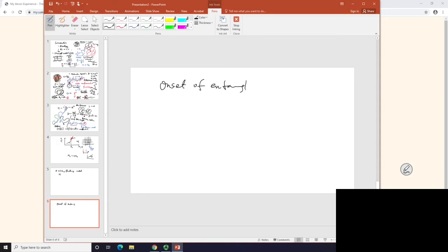In other words, as my molecular weight starts to increase and approach M_E, my N, which increases with chain length, starts to increase to a value. Guess what? It turns out this value is about 6 to 7.